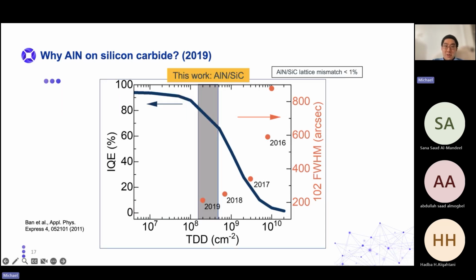So our initial work in our group was on aluminum nitride on silicon carbide, because the lattice mismatch between aluminum nitride and silicon carbide is less than 1%. So material is much easier to grow at much higher quality. And another added bonus is that even though silicon carbide is absorbing to ultraviolet light, it is possible to remove the silicon carbide after the growth of aluminum nitride and our UVLED material on top with a flip chip process that we'll go into quickly after this.